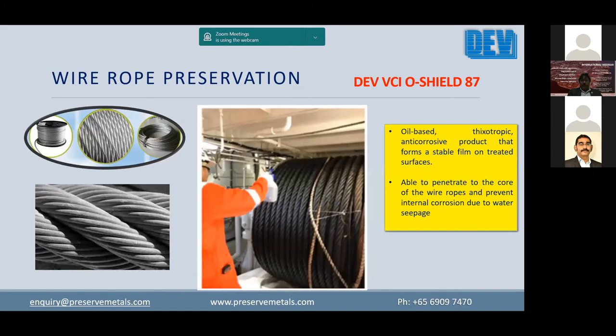This is the one we discussed earlier, O-Shield 87, for preserving wire ropes. Especially this will ensure that there is no internal corrosion in the wire ropes, because when the wire ropes are exposed to rain and water, the water can seep through the wire strands and then initiate corrosion from the core. That is prevented and eliminated with the use of this O-Shield 87, because it penetrates the core and protects the wire rope from the center, while the grease protects the external.